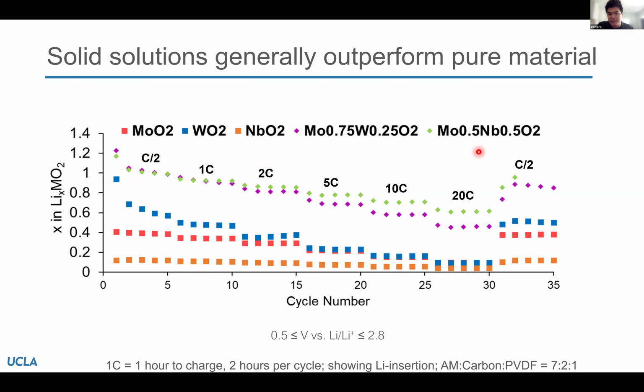And so we can see, and this is true across battery materials, that as you charge your batteries faster, you're able to access less of that capacity. However, when we compare our battery materials, we can see that we're able to get a lot more of our capacity at different charging speeds compared to just the pure materials. And so this is just to show that the solid solutions do outperform their single element counterparts. This could be understood because, well, we'll talk about phase transition mechanisms, but also it is widely known that if you incorporate the right element into your structure, this can increase lithium ion diffusion, which again is a critical requirement for fast charging in batteries.